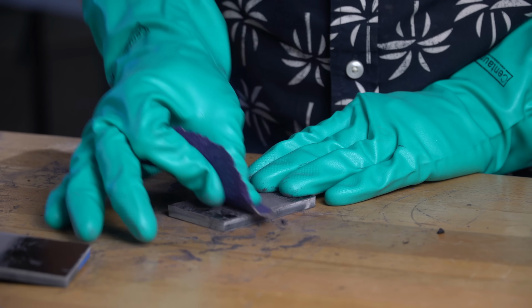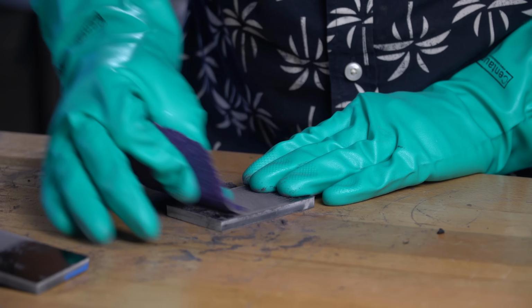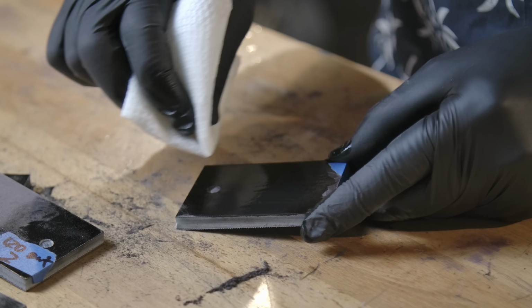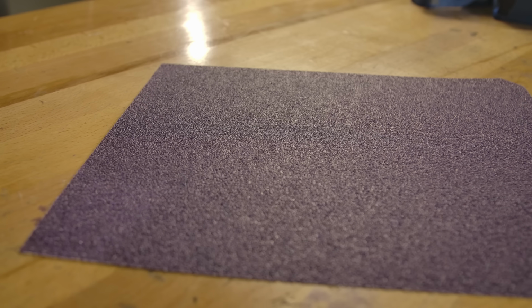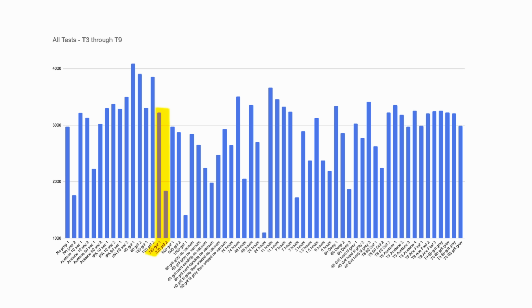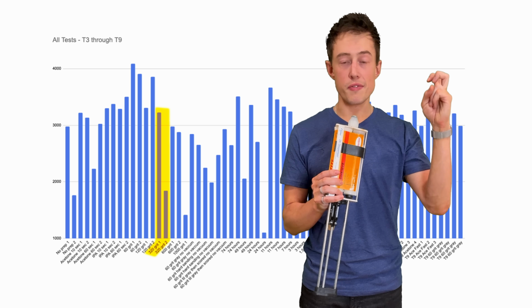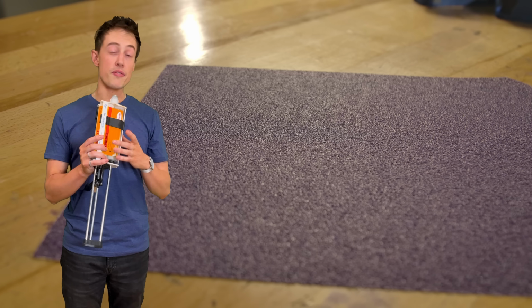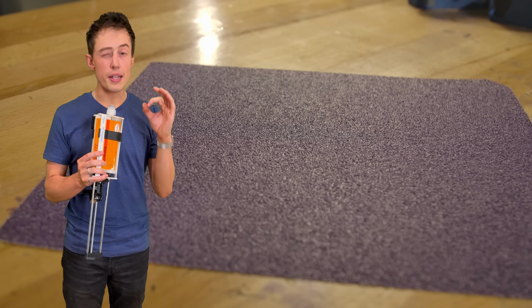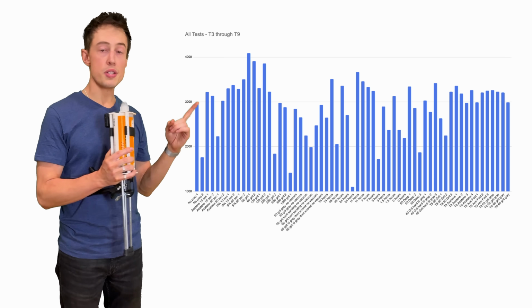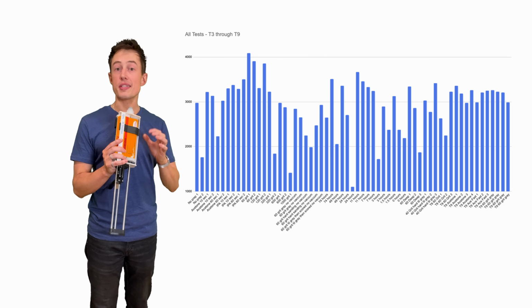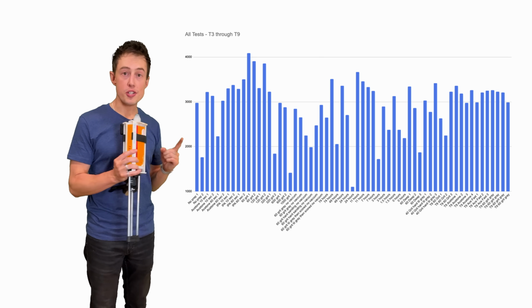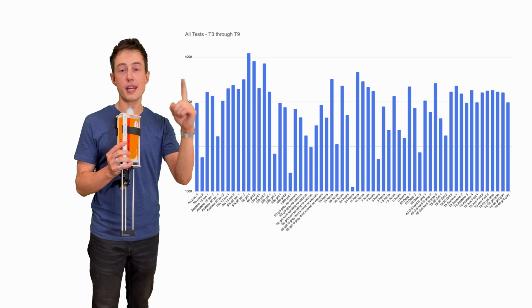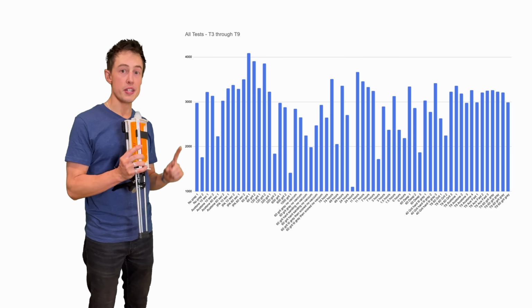In many of these runs, I was sanding and using IPA right after, but I wasn't doing acetone beforehand. Maybe the sandpaper I used had a strong enough mold release on it that the IPA couldn't get rid of it. That might explain some of the huge deviations in earlier tests. And maybe my fresh sheets of sandpaper weren't that fresh after all. If these sheets were contaminated with just a little bit of oil or grease, these results would start to make a lot more sense. This is especially true because I picked fresh sheets of sandpaper before every new test series, but not before every test coupon.